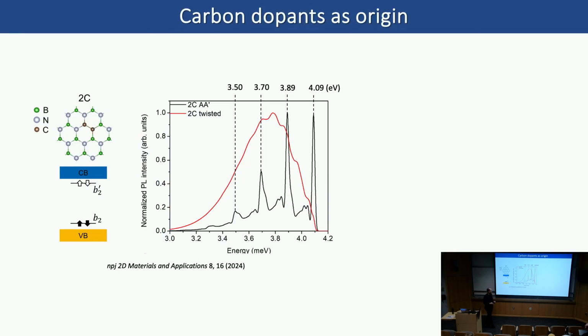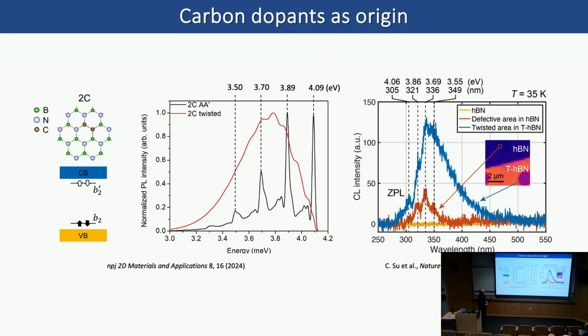But the question is, what are the origins of these defect emissions? What are they? It's still debated. People are still debating what this very famous 4eV emitter is. One work that did a pretty good job in predicting the spectrum is from this paper, which shows almost a complete mirror symmetry. So they go from 409 back to 350. This is going from the left to the right. And you could see they almost reproduce the shape of what we're seeing in our CL experiment. So we tend to believe, okay, maybe it's a double carbon, called the carbon dimer, where one carbon is substituting a boron atom, and the other carbon is substituting a nitrogen atom. So that's maybe the origin. And there is also some other work saying it's a self-trapped exciton.